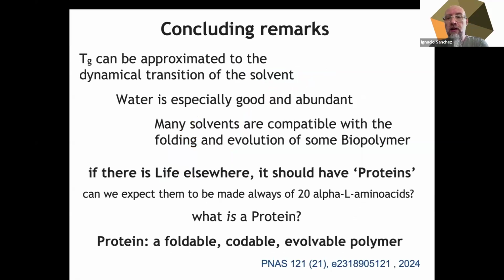Summing up, in our solvents, the glass transition temperature of the polymer can be approximated to the dynamical transition of the solvent, as we see for biopolymers in water. Water seems to be especially good for biopolymer folding and evolution, and it's also abundant in the universe, so it makes sense that we are water-based life. However, many other solvents are compatible with the folding and evolution of some biopolymer.